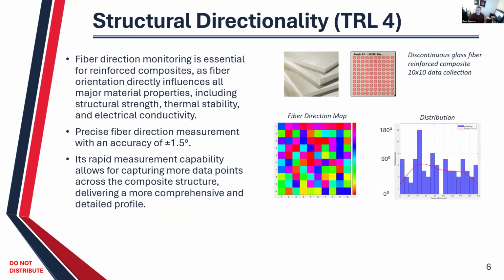To go into some case studies and examples, for the structural directionality capability, one example within the composite industry, which IACMI is familiar with, is monitoring fiber direction. We can relate to a pseudo fiber direction from our inspection measurement. This supports woven structures or non-woven, discontinuous materials. And we're also material agnostic. It doesn't matter if it's carbon fiber or glass reinforced. What we're monitoring is the anisotropic thermal expansion that occurs with the fibers.